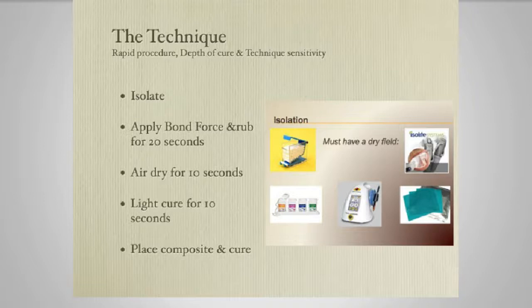The reason this composite cures so fast is what's called the RAP technology that Tokuyama has. This is a radical amplified photopolymerization initiator. This initiator basically balances out the high polymerization activity that's needed to cure the composite with the short exposure time that you need. It also allows it to have stability in ambient light, which is that 90 seconds that lets you work in there.